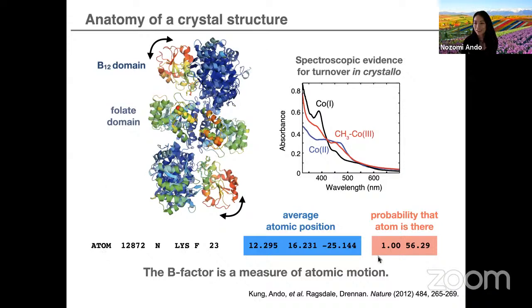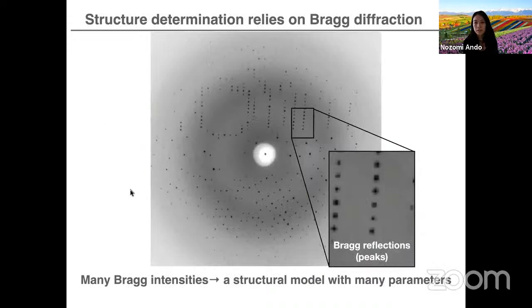And also, I want to reiterate that the structure is still a model. We're trying to get a model of all of the coordinates of every atom and a model for its motion that is consistent with the data. So the data for crystallography is Bragg diffraction. Here I'm showing a very nice diffraction image. We all recognize it to be diffraction because it has these nice spots, which we call Bragg reflections or peaks. And in conventional crystallography, the measurement of these intensities, which we call Bragg intensities, many measurements of those, so we need to have many observations, is what allows us to refine a structural model that has many parameters like the one I just showed you.